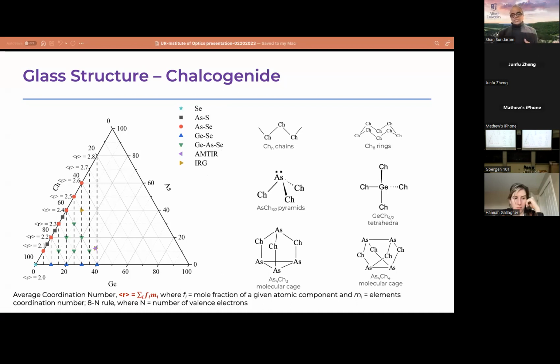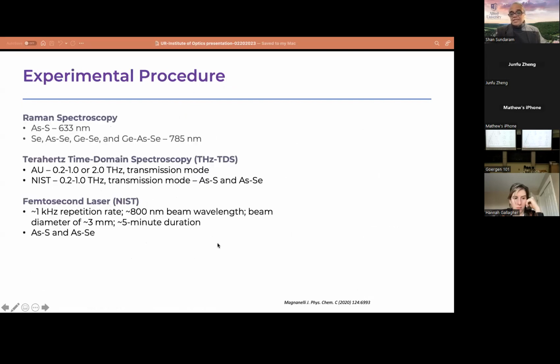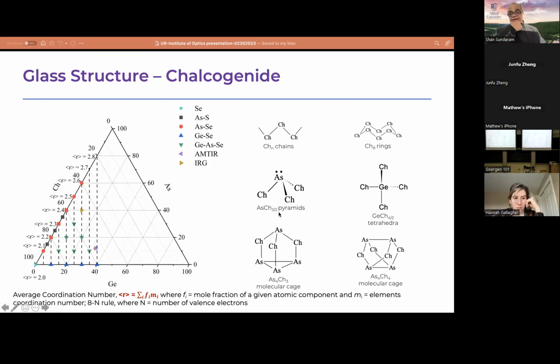We selected these compositions, but there is a method to madness here. You can see we have put it all in what we call a ternary diagram. This is germanium on this axis, arsenic, and then we're varying this chalcogen element, either sulfur or selenium. So once again, we have mapped our data points. Some of the glasses we have made, some we purchased, and some we collected from our collaborators. You can notice one of our collaborators is from NIST. We also wanted to compare our measurements to the measurements done at NIST. We wanted to see how close we are.